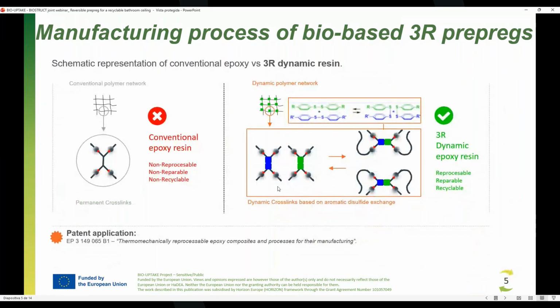So as I said, what we are using here is a bio-based, in this case, 3R dynamic resin. The advantage this kind of resin has is that, unlike conventional epoxy resins, which are non-reprocessable, non-repairable, and non-recyclable, the dynamic epoxy resins, thanks to the dynamic or reversible aromatic disulfide bonds they have in their structure, offer the possibility of being reprocessed, repaired, and recycled even after curing. This is a technology that was patented by CIDETEC some years ago, and is what we are applying here.